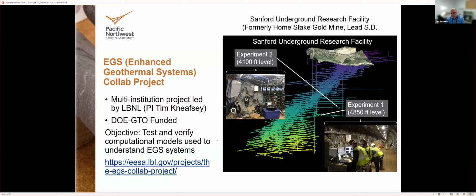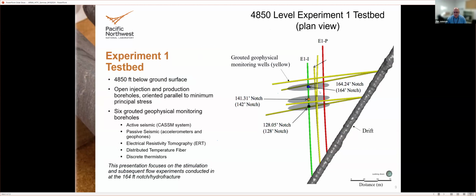So we had two test beds here. One was on the 4850 level, and one was on the 4100 level. And we're going to start with an experiment we did on the 4850 level to kick things off. This was our first experimental test bed. We have the mine drift here, and then we had several subhorizontal wells drilled off of the mine drift, and the direction of those wells was chosen because we were going to hydrofracture. We were anticipating the hydrofractures to have an orientation as shown here in the shaded areas.